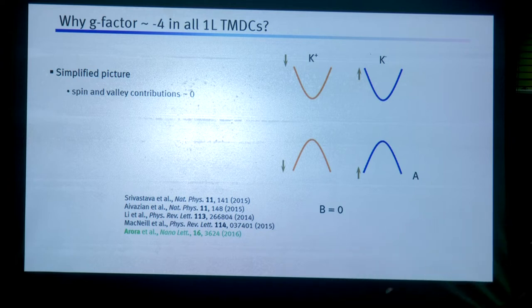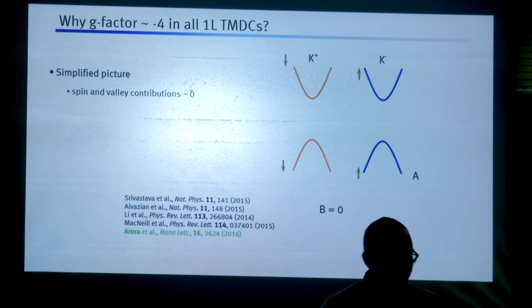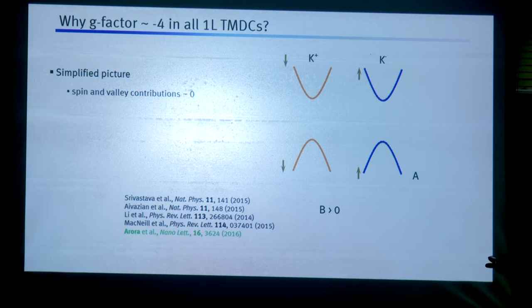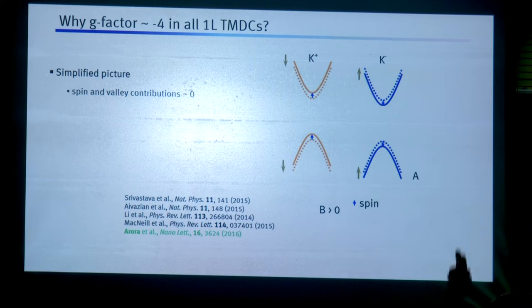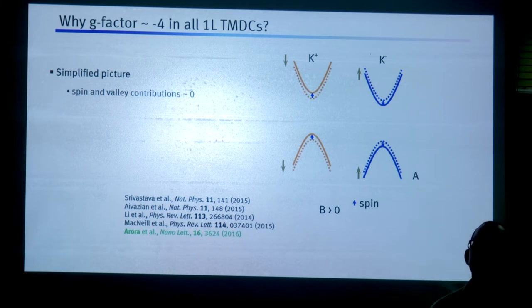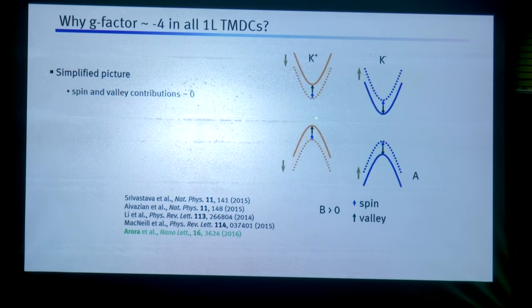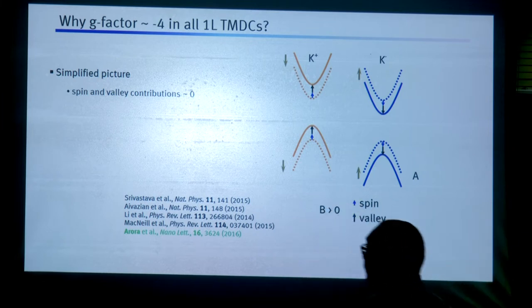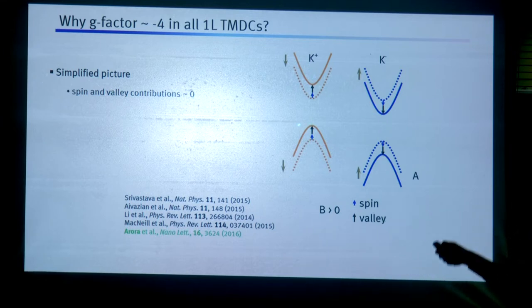One. At the bottom of the conduction band or top of the valence band, there are carriers which have some spins. So these spins, if I apply magnetic field, they move in the same direction because the spin is conserved in an optical transition. The spin stays the same, so both spins move by the same amount. So this does not change the exciton energy. Okay. The other moment which is there is coupled to these valleys, that's called the valley magnetic moment. And when the magnetic field couples to that, the valley magnetic moment also takes the two bands in the same direction again. Again, no energy change. So this moves up, this moves down, but the total energy difference stays the same. No degeneracy lift so far.